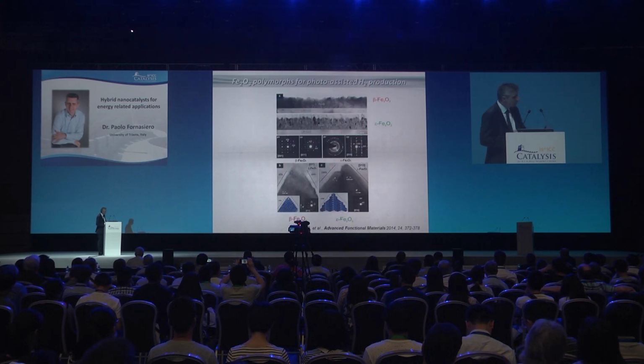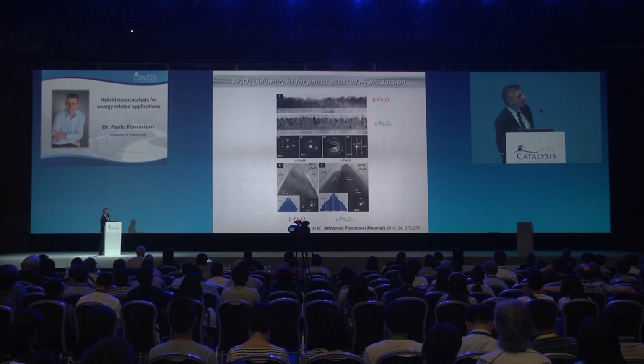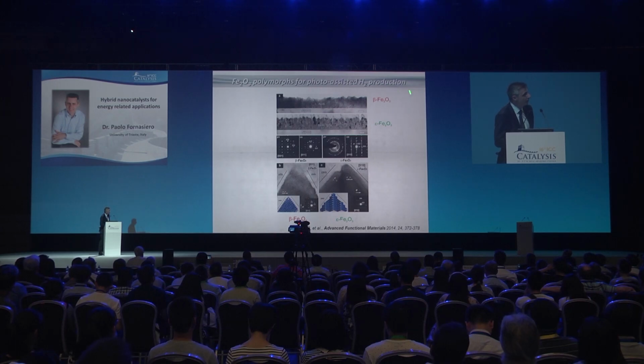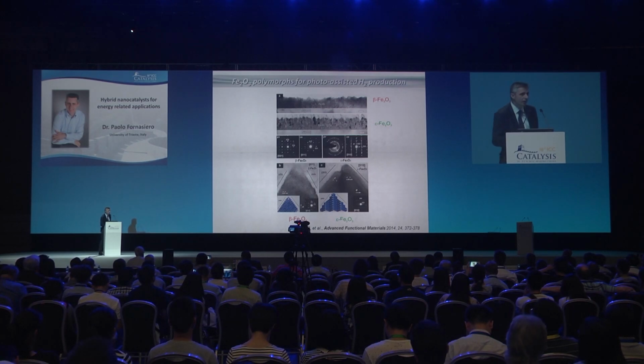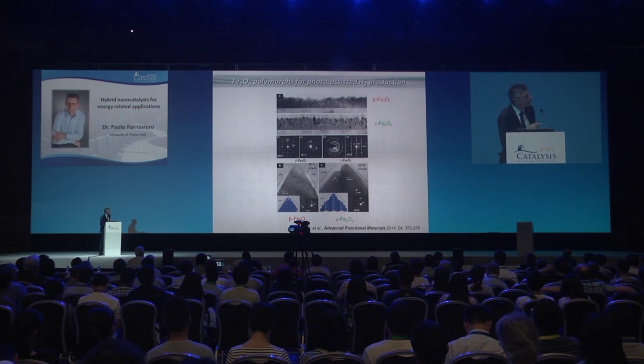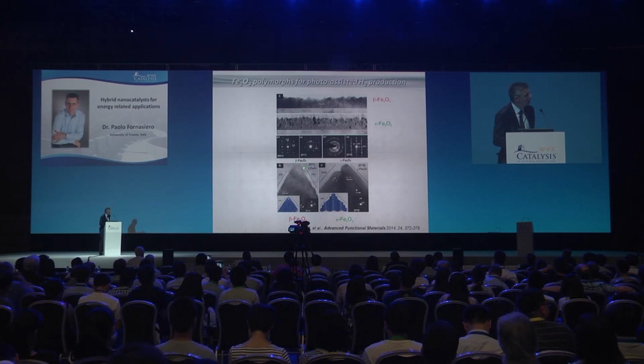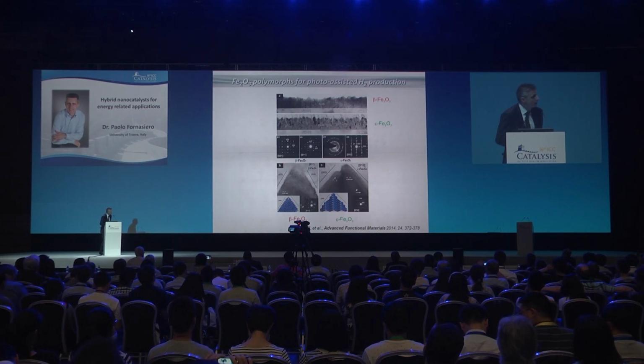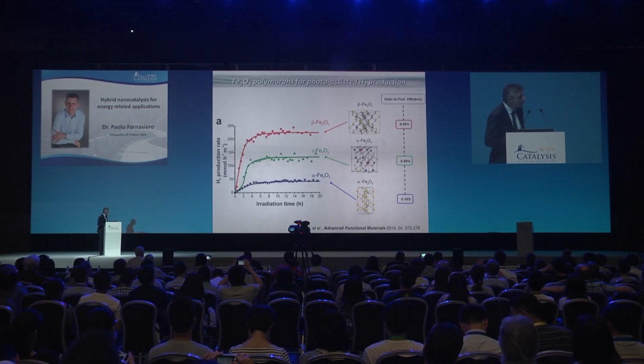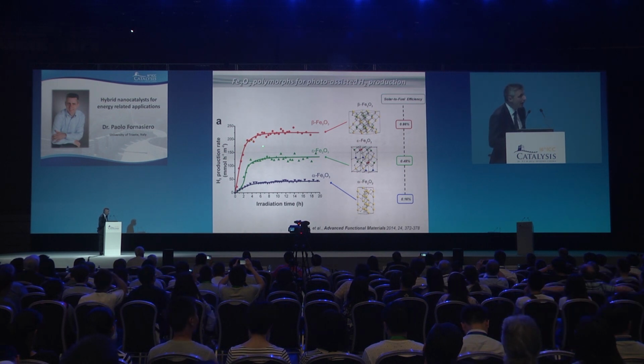iron oxide should work. So far it has been used a lot by Michael Grätzel, for instance, for oxidation reactions, but we managed to obtain supported polymorphs of iron oxide, including hematite, and the trick is to make not bulk material, not a dense film, but this type of pyramid-like tips, in which you have a mixture of iron 2 and iron 3. And indeed, if you do that, you can get hydrogen photocatalytically.